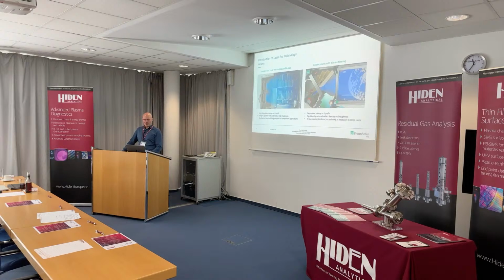And on the right side, we have some scheme of such a particle filter. As you see, the plasma is generated at the graphite. Then the particles are flying straight in some structure, and only the pure plasma is going to the deposition chamber. And so we get smoother coatings. But of course, if you have a filter, then you always have some reduction in deposition rate. So we have 50%, which is good, but we still have particles in there. And in this case, up to 1 micrometer per hour for a fully loaded chamber.